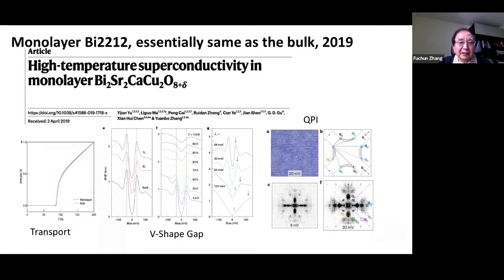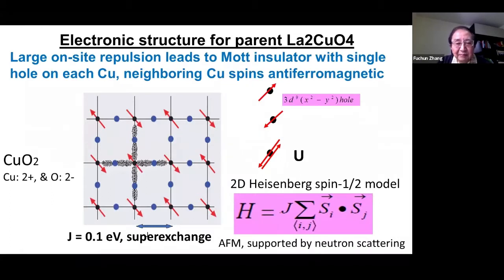And actually, a recent paper by Yuanbo Zhang at Fudan University, published last year, has confirmed that two-dimensionality is important. Only one layer, actually in that compound they have two layers, and the properties like Tc and the STM measurement are essentially the same as the bulk. So that means the third dimension really plays not much role. So we can focus on 2D systems, which makes life much simpler. We have the copper and oxygen plane, and we can temporarily ignore all other elements.